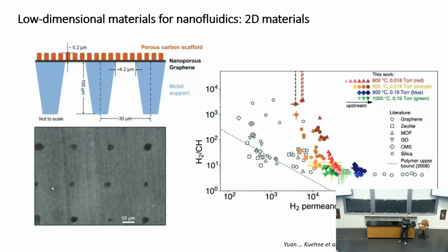The thinner the membrane, the higher the permeance, the smaller the defect, and the more the possibility that it's actually selective. So here's selectivity of H2 versus methane plotted against permeance. And here's the polymer membrane limit, assuming a membrane of 1 micrometer thickness. And you can actually see these graphene results here are indeed higher permeance and higher selectivity, but it's always a trade-off. As you can see in this Robeson plot, it's a trade-off of permeance versus selectivity.